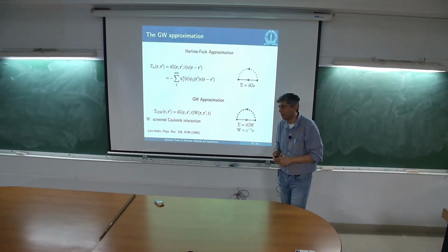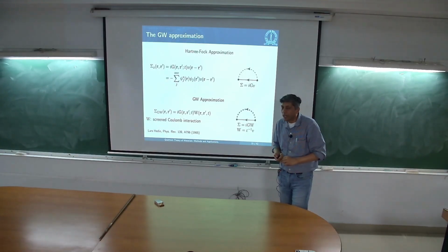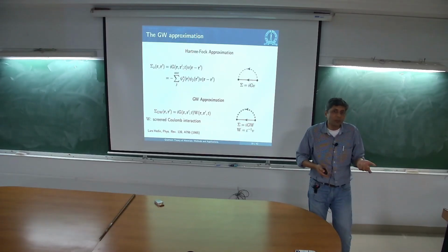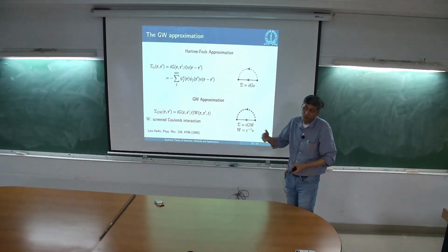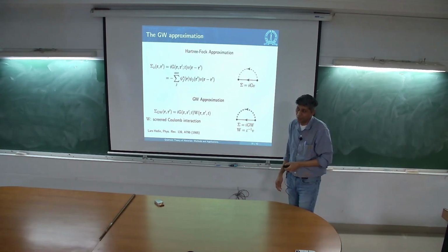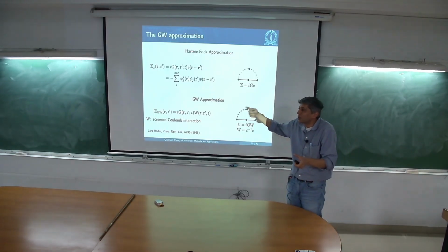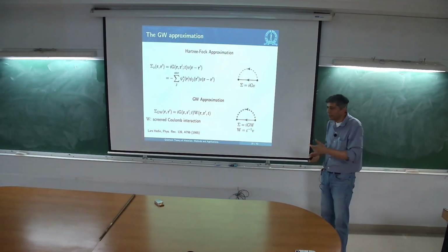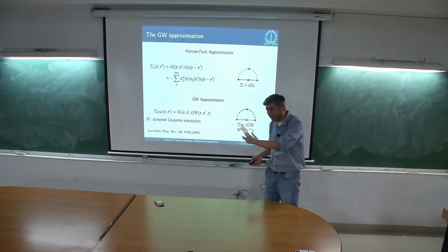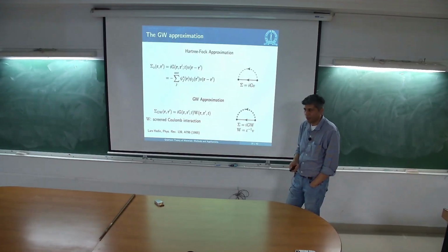So if you, let's say, start from HSE, which already has some corrections of self-interaction, then it should give much better results, in principle. But the question becomes how important the vertex correction becomes. The vertex correction will depend on what you have built into the G and the W, because every time you're doing a different G and a different W, it's an effective G and an effective W. So the vertex becomes somewhat important in the case of HSE. So what works best generally? LDA or PBE, the simplest thing works the best. PBE plus G0W0 works. LDA is what I use, but LDA or PBE is also perfectly fine.